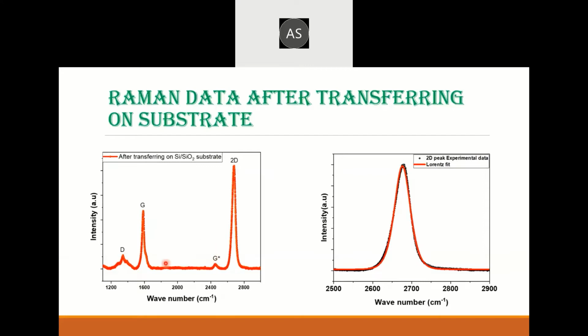And then if we look at the ID by IG ratio of these two modes, we find that the defect peak is not prominent. So we have not introduced any kind of defect when transferring. Also we have fitted this 2D peak with a Lorentzian, and we find that it fits a single Lorentzian, which indicates that it's a monolayer. So this is the first experiment that we did.